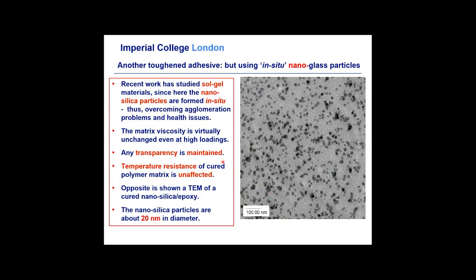Here's the more recent work we've been looking at. This is another toughened adhesive, but now using in situ nano glass particles. We use a sol gel technology, so that these glass particles, this is a transmission electron micrograph, they're about 20 nanometers in diameter. You get very good dispersion, which you need to get good toughness, but they're formed in situ, so this leads to the good dispersion and also overcomes any health issues. Since these nanoparticles are never free in the atmosphere, they're always contained within the adhesive because they're formed in situ. Also, you get a very low viscosity for the matrix, which means you can use it also for composites, especially for resin transfer molding. You still maintain transparency, you still maintain temperature resistance. So it's another way of toughening the adhesive.